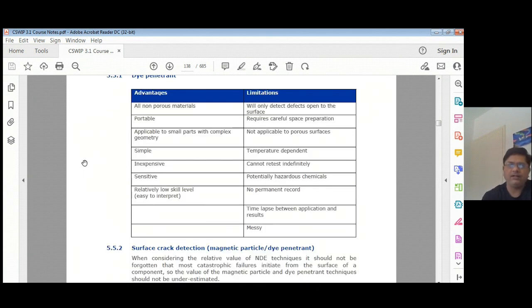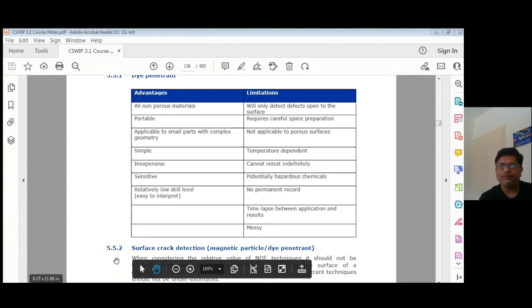So what are the benefits and limitations? You can use it on all non-porous material. It's very portable. Only three cans are required: basically penetrant, remover, and the white contrast, and of course a few lint-free cloths for wiping. It is applicable to small parts with complex geometry. It is simple, inexpensive, sensitive, and requires relatively low skill. You can only detect surface defects. It requires careful surface preparation. It is not applicable to porous material surfaces. It is temperature dependent, and cannot be retested indefinitely. Once the test is done, you basically cannot retest again and again in this method.